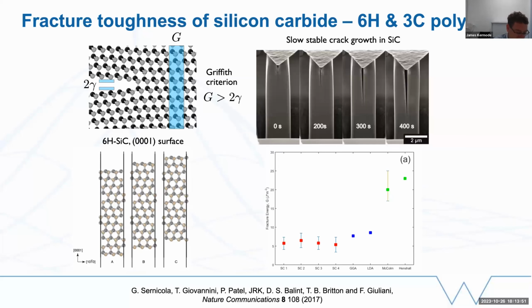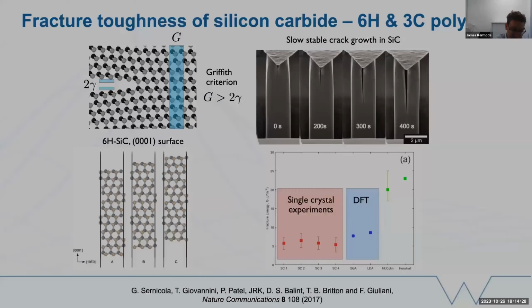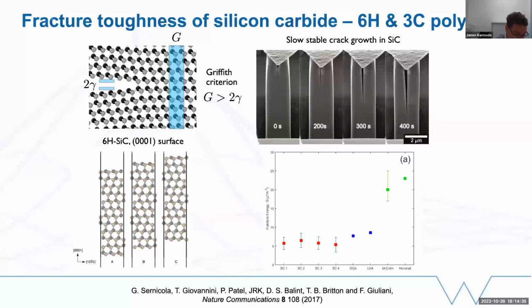This is some work we did a few years ago in silicon carbide in this direction. We had to be a bit careful here because we had to look at the right polymorph of silicon carbide. We had to think about different possible cleavage planes and different possible surface terminations. But if you take all that into account and calibrate carefully with very precise double cantilever experiments where cracks are stabilized for a very long time, so 400 seconds, the crack is growing only a few microns, and we look at the fracture energy that's required in different experimental samples, shown in red, and with the density functional theory direct calculations shown in blue, we get good agreement, much better agreement than with previous experiments, which are shown in green there,